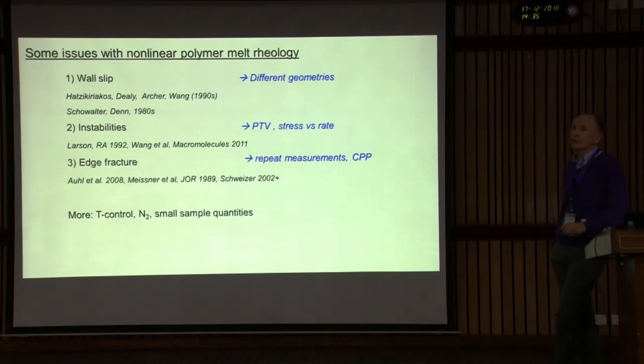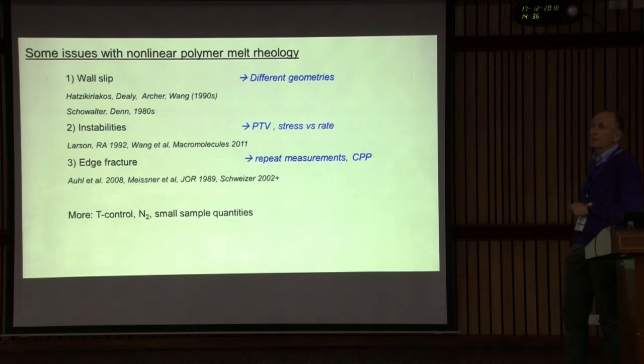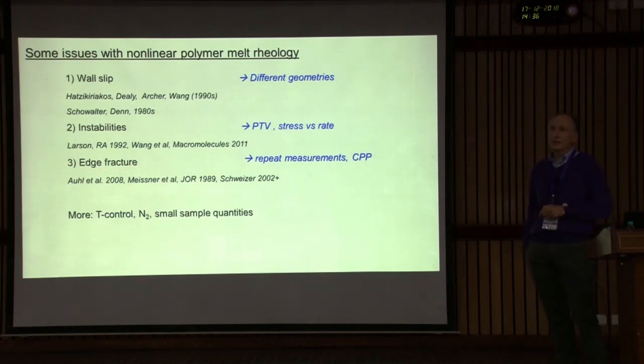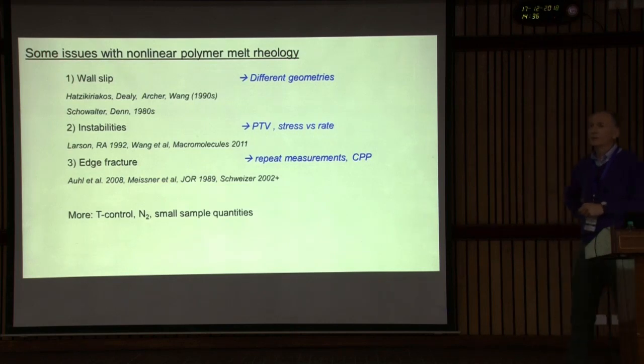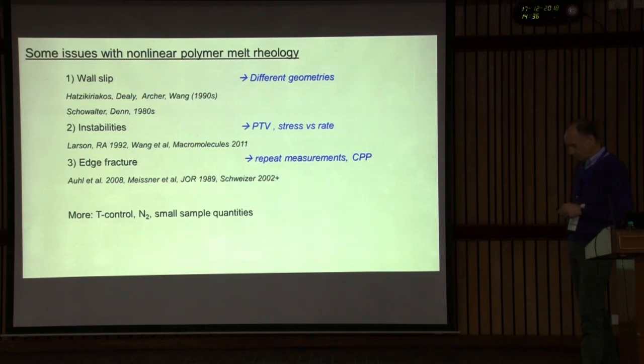The second issue is instabilities, most notably shear banding. In this case, you can either measure the velocity profile or measure stress versus rate and check whether there is a plateau, which you can associate with banding. Finally, the topic of today's talk: edge fracture. To avoid this, actually the answer is you cannot. But you need to do repeat measurements to make sure that edge fracture does not affect your measurements, or you can use a special geometry, the CPP, which I will discuss in a minute.